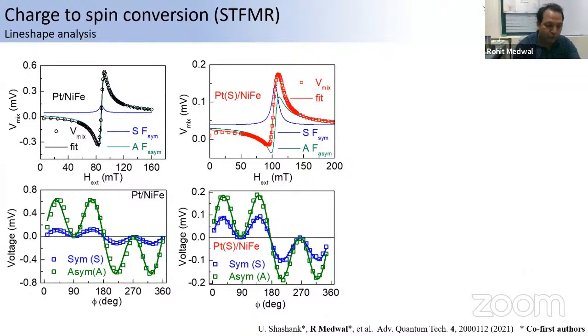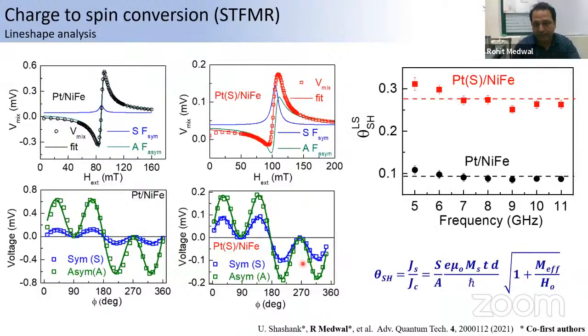The symmetric component corresponds to the spin to charge conversion, and the antisymmetric component is because of the Oersted field. And we can see that the symmetric component in the PtS is quite a bit higher compared to the pure Pt. This clearly indicates that we have a higher spin to charge conversion. And this is the spin orbit torque symmetry, which is sin 2 theta cos theta, and which is also not broken after the implantation, because we are doing low energy implantation to keep the symmetries of the platinum crystal intact. When we do the analysis, taking the symmetric to antisymmetric component ratio and putting in all the constant parameters of the system, we are able to observe a 3 times enhancement, or you can say the 30% spin to charge conversion in the PtS.